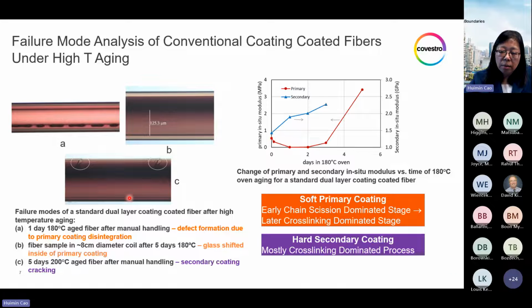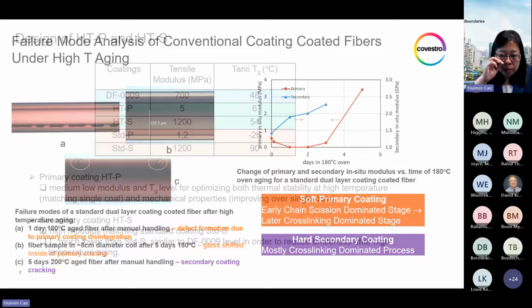Picture C is the fiber after 5 days at 200 degrees C, and after manual handling, the secondary coating showed cracking. This is an indication of embrittlement. So in summary, at high temperature, the soft primary coating undergoes first a chain scission dominated process, and then later a cross-linking dominated stage, into a disintegrated, fragile material. And the hard secondary coating undergoes mostly a cross-linking dominated process into a brittle material.